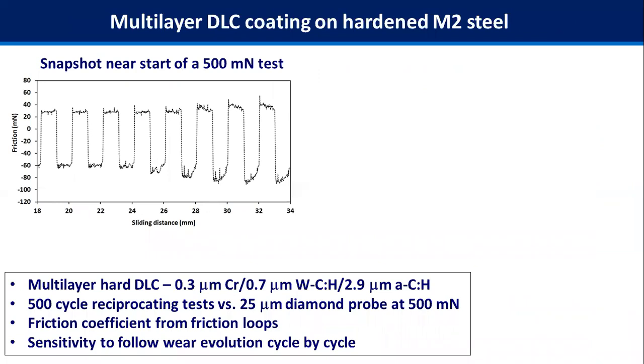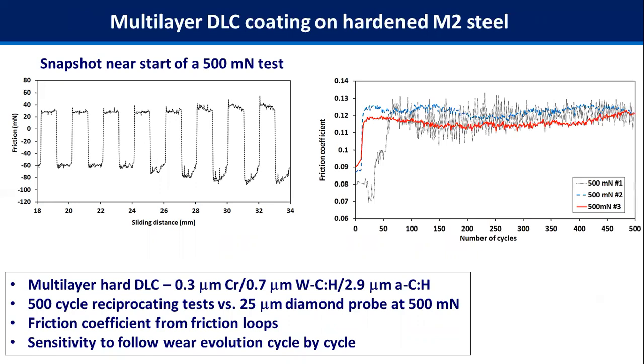So this is an example of the latter. It's a multi-layer diamond-like carbon coating deposited on hardened M2 tool steel. And this is a snapshot near the start of a 500 cycle test at 500 millinewtons sliding against a 25 micron end radius diamond probe. And what we can see is over a relatively small number of cycles, the friction starts to increase, and we've got the sensitivity to follow the wear evolution cycle by cycle. If we convert the raw friction trace into friction loops and then take the average friction over a friction loop, we can easily plot friction coefficient against number of cycles. And we can see here that we can pick up quite nicely this increase in friction occurring near the beginning of the test in these two tests here.